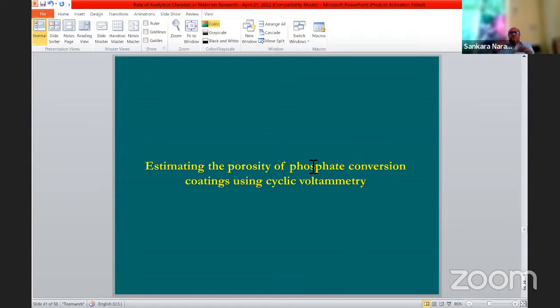There is no such thing as a completely pore-free coating. There will be some amount of porosity. Porosity is like a hole, an uncovered area. Through that, moisture or electrolyte can penetrate and start corrosion on the base. So how to estimate the porosity of a conversion coating, phosphate conversion? How can cyclic voltammetry be used for that?